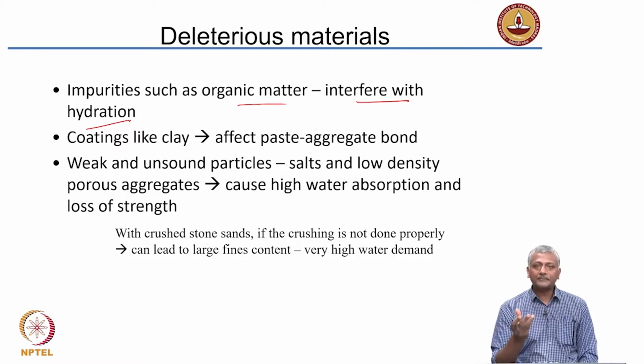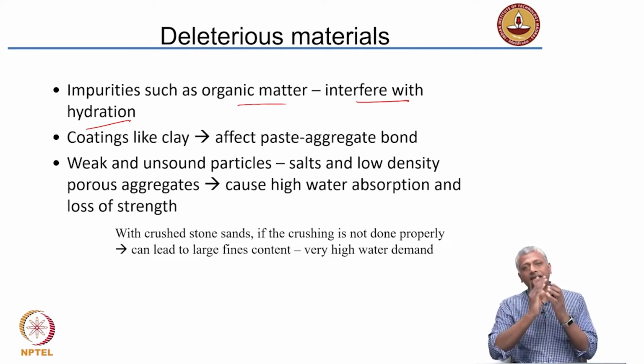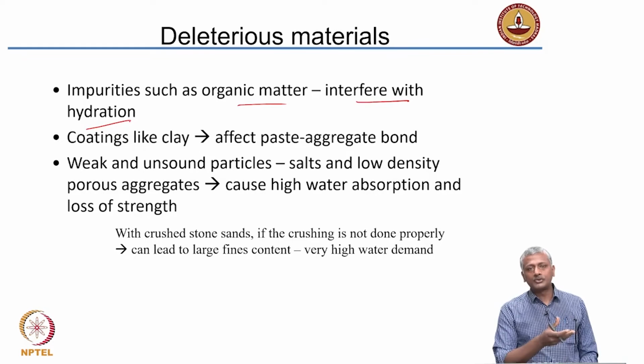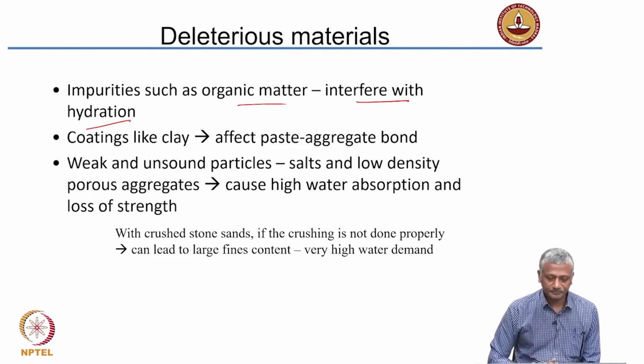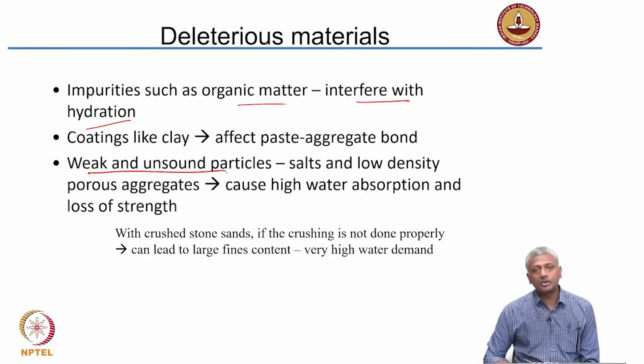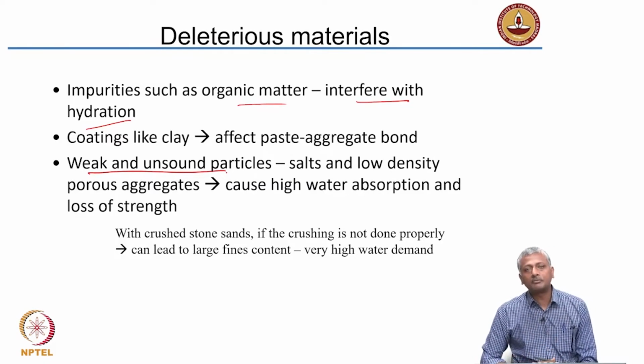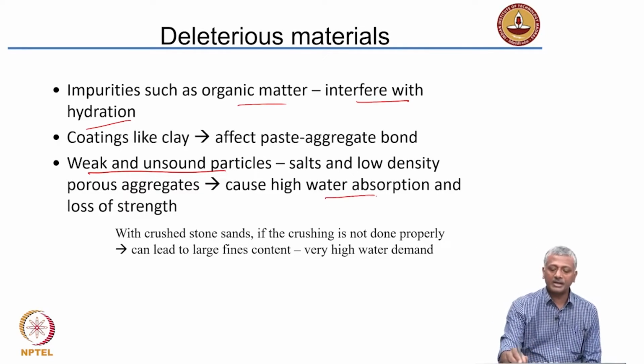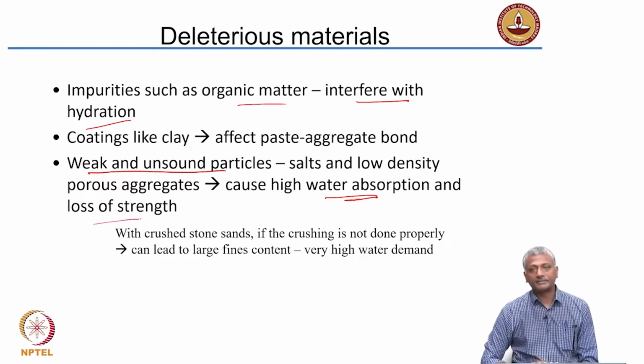Now, when you have clay, when you break down the aggregate and it has got clay in it, the clay may start forming a lining on the surface. Sometimes aggregate that you get is dirty, okay, that is because of the clay lining on top. If you do not clean it up well before using it, that will affect the paste aggregate bond. The paste has to bond well with the aggregate, and if you have a lining of clay on top of the aggregate, it is going to spoil the bond. The other aspect is weak and unsound particles. As I said, when you collect aggregate from riverbeds, you need to be very careful about finding weak and unsound particles. These can cause very high water absorption and loss of strength.